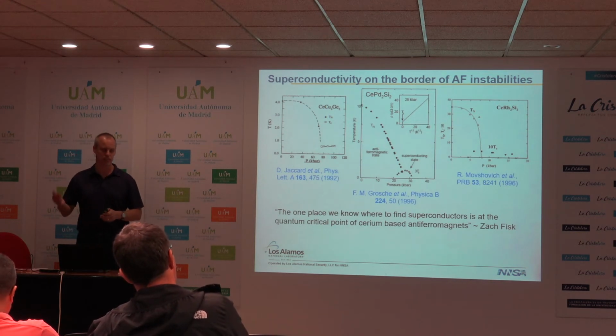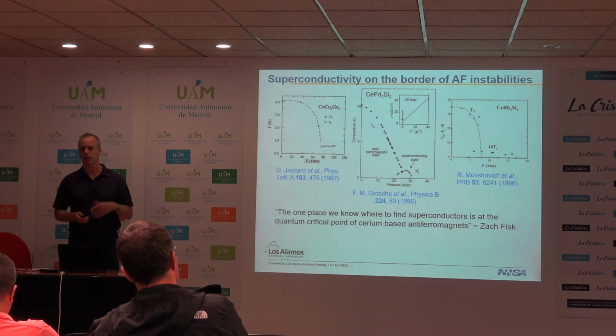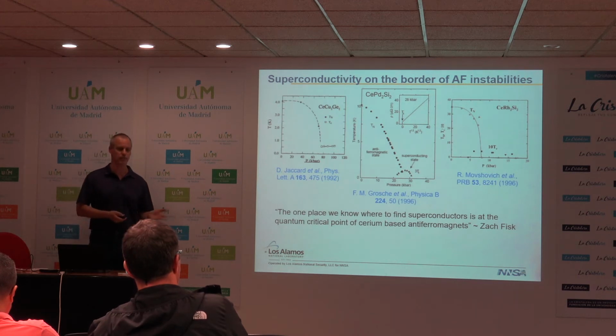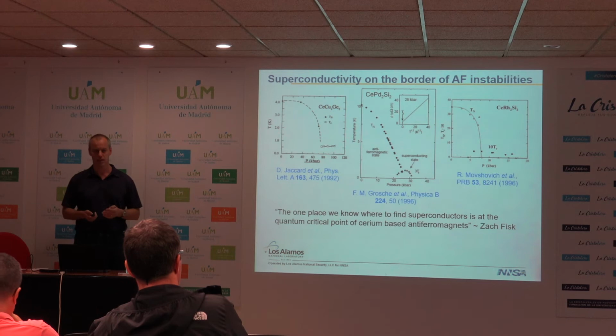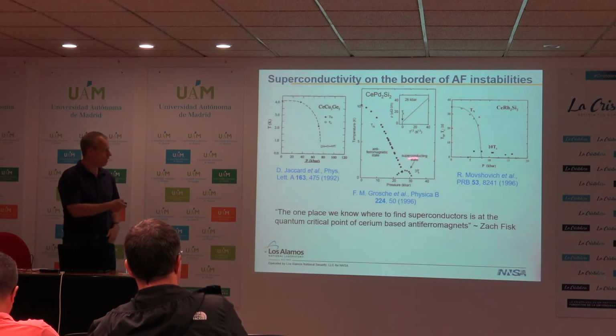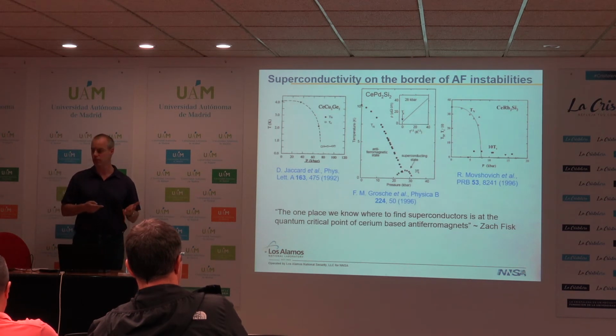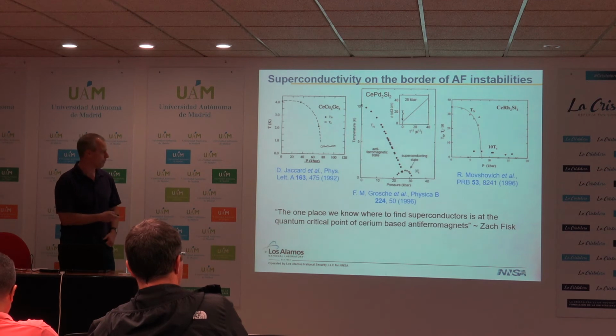That's consistent with a more conventional Hertz-Millis-Moriya like theory of quantum criticality. Sometimes we see sublinear behavior. So in the 115s, we see T to the 0.8. So the value of the power law is not well understood. But in fact, heavy fermions offer clean systems in which to explore quantum criticality, and we see that those fluctuations in some way promote superconductivity.